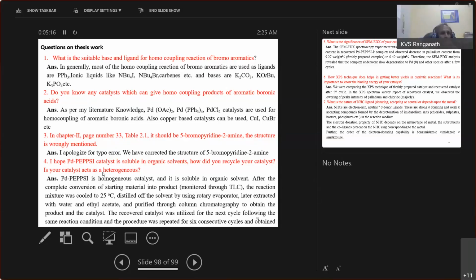I hope the palladium PEPPSI catalyst is soluble in organic solvent. How did you recycle your catalyst? Does your catalyst act as a heterogeneous catalyst? Palladium PEPPSI is a homogeneous catalyst. It is soluble in organic solvent. After the complete conversion of starting materials into product, the reaction mixture was cooled to 25 degrees and the solvent was distilled off using a rotary evaporator. Later it was extracted with water and ethyl acetate and purified through column chromatography.